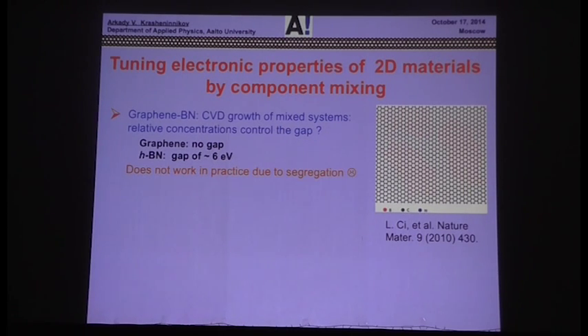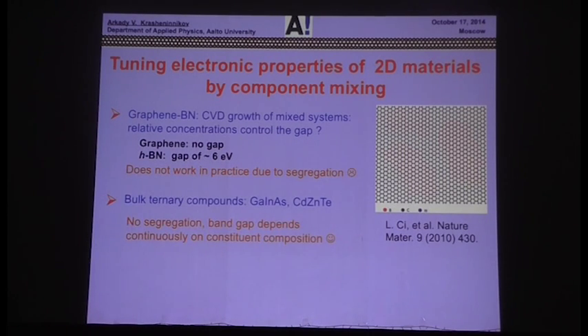Still, I think there is a way around that if you grow these systems on metals like ruthenium, which strongly interact with the growing layer. You may still get some sort of distribution, but it's not trivial and not obvious that the distribution will be homogeneous. However, we do know that in bulk ternary semiconductor compounds, this approach works very nicely. You can tune the gap depending on the concentration of the constituent elements in your sample.